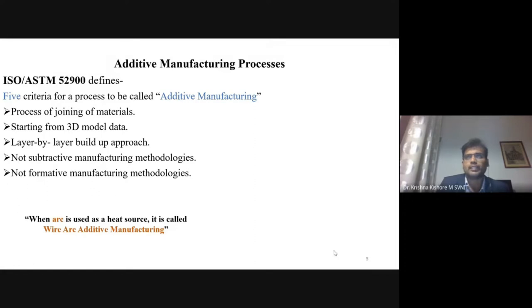So there is a deposition that is happening, and for this deposition there should be something that is melting. For melting this wire, we are using an arc as a heat source, and these molten droplets will be deposited on the substrate. We are integrating with the CAM software such that it will move in a layer by layer fashion required for our component.